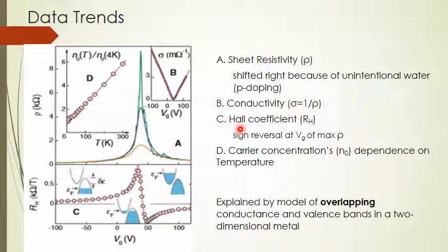However, in the state of mixed holes and electrons, sigma conductivity changes insignificantly with gate voltage, which indicates a carrier substitution while Hall resistivity reverses its sign, exemplifying its proportionality to the difference in density of electrons and holes. With no gate voltage or electric field doping, few-layer graphene acted as a hole metal due to unintentional water doping, which, like I talked about, causes shift to the right. In an annealed vacuum, they found that it could be shifted leftward.